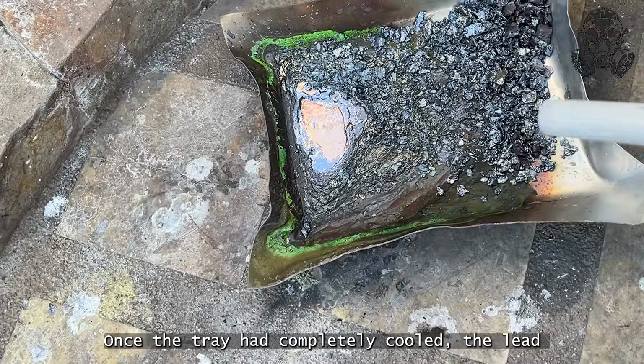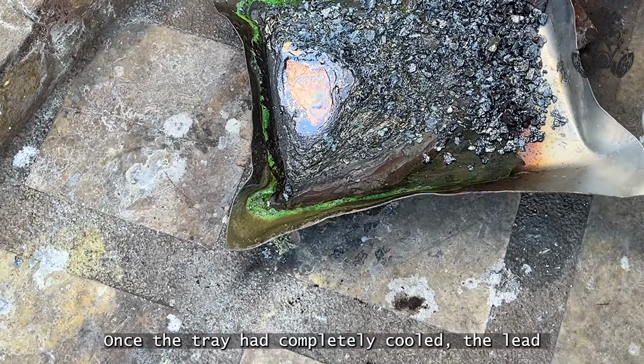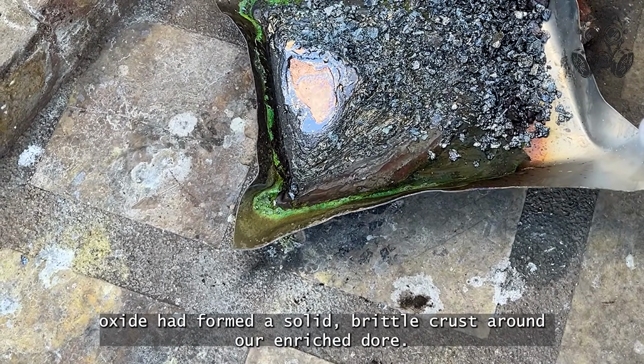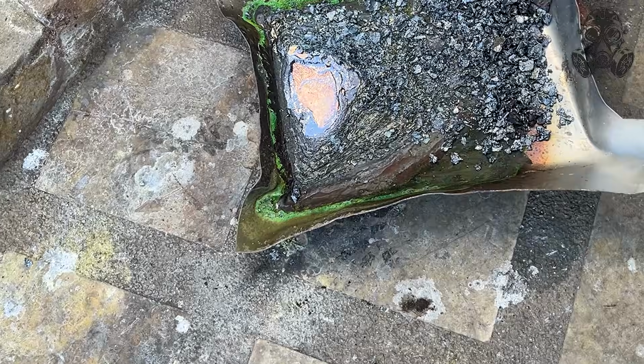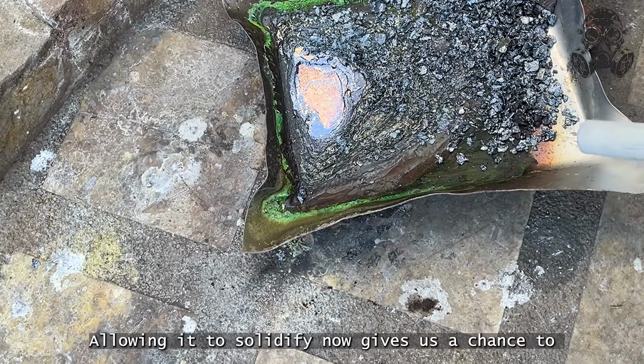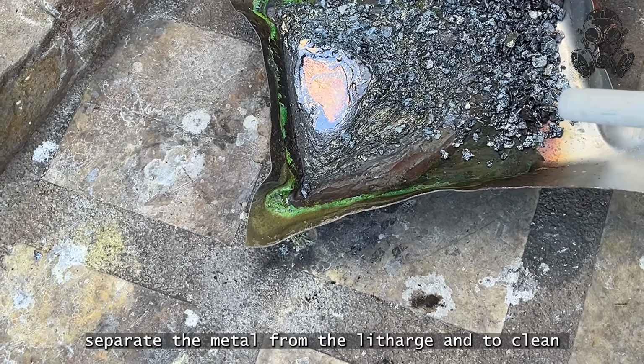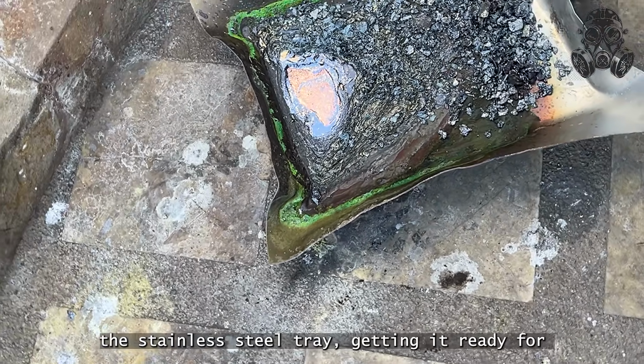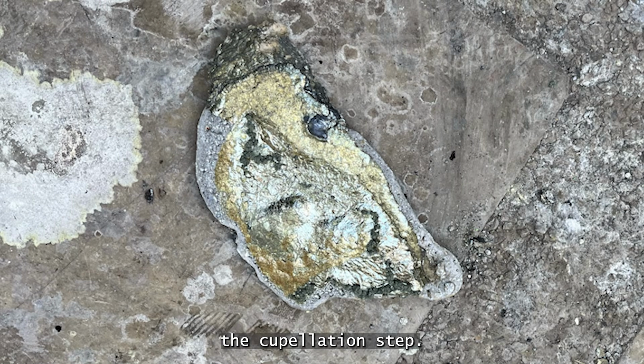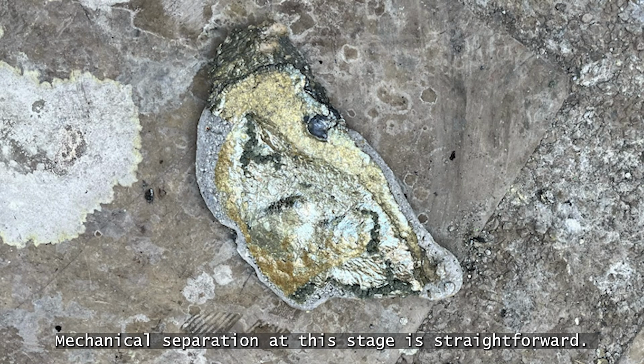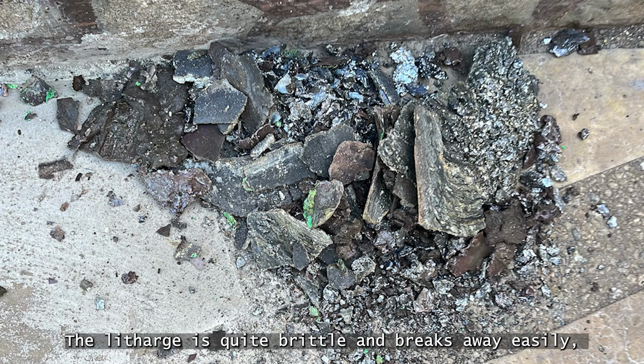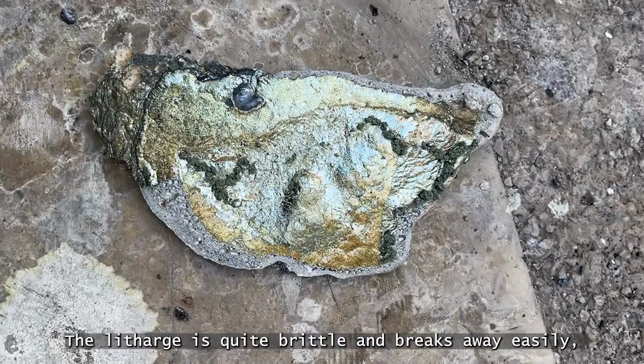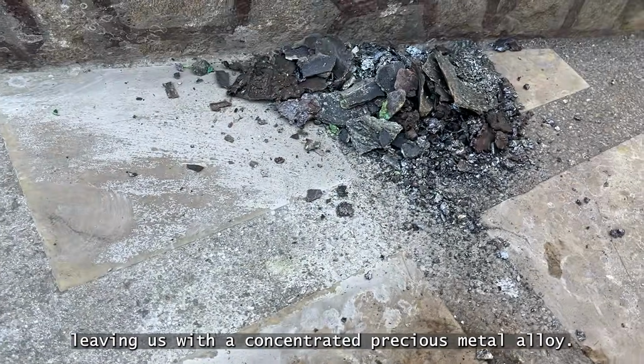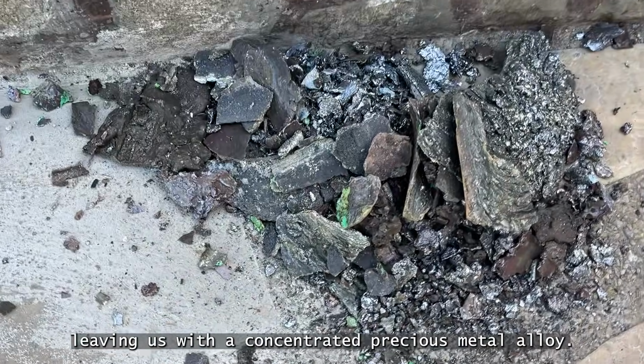Once the tray had completely cooled, the lead oxide had formed a solid, brittle crust around our enriched doré. Allowing it to solidify now gives us a chance to separate the metal from the litharge and to clean the stainless steel tray, getting it ready for the cupellation step. Mechanical separation at this stage is straightforward. The litharge is quite brittle and breaks away easily, leaving us with a concentrated precious metal alloy.